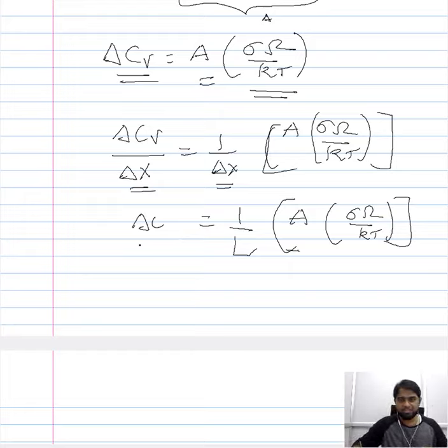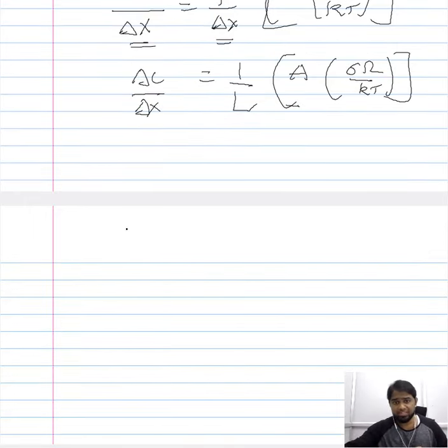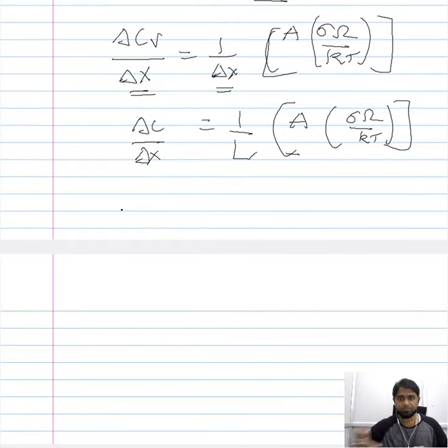By introducing this L, we are considering not just the difference, but the gradient in the concentration of vacancies. The reason we want to consider the gradient is because the difference in the concentration of vacancies is introduced by the difference in the mechanical or loading condition, and this is dominant, or comparable to the other values of energy of formation, because we are talking about high temperature.